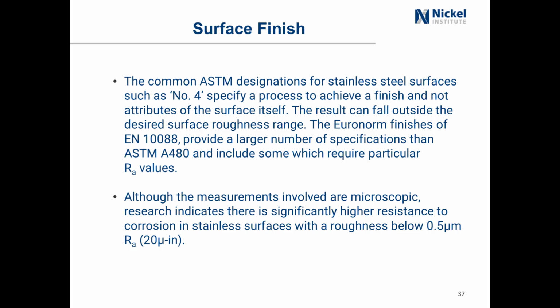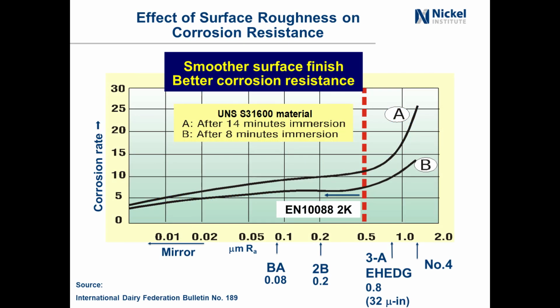And although the measurements involved are microscopic, research indicates there is significantly higher resistance to corrosion in stainless steel surfaces with a roughness below 0.5 micrometers or 20 microinches. And that's shown in this graph. This was developed by the International Dairy Federation and reported in Bulletin 189. And this is just showing surface roughness in micrometers along the bottom. And then this is just a relative corrosion rate. It's not an actual value, it's just relative.